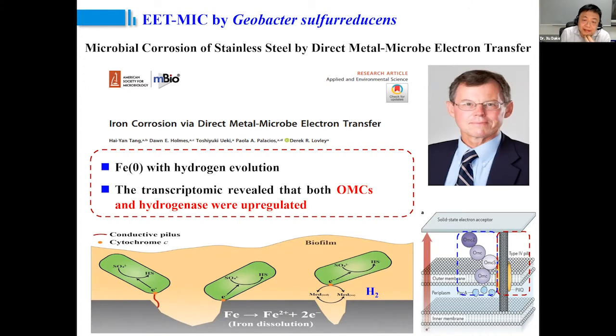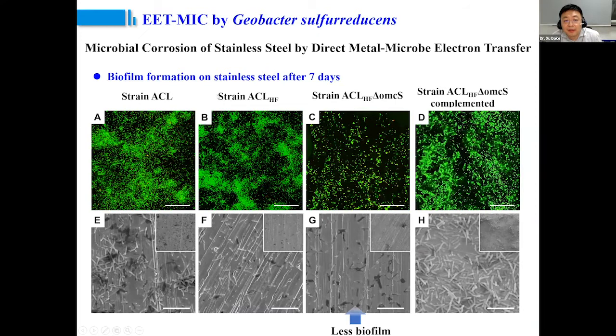So when I was a visiting professor in Derek's group, we made some new mutants and wanted to avoid the influence of hydrogen. So we changed carbon steel or zero-valent iron into stainless steel, and we made a fresh water medium. In this medium, fumarate is the sole electron acceptor, and stainless steel is the sole electron donor. So if MIC occurs, the only electron transfer pathway is Geobacter obtaining electrons from stainless steel and then passing them to the fumarate. So we made a hydrogenase deletion mutant, and then we deleted the cytochrome OmcS of this strain, and then we complemented it back into the mutant.